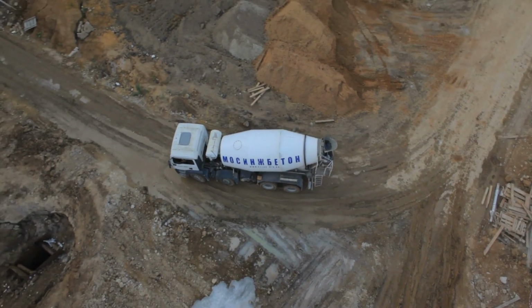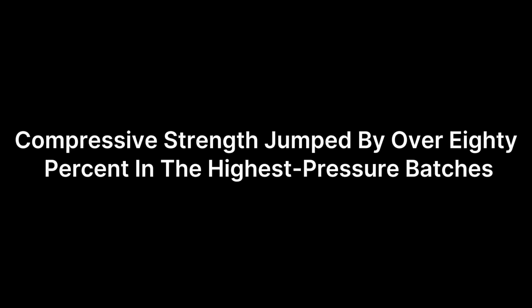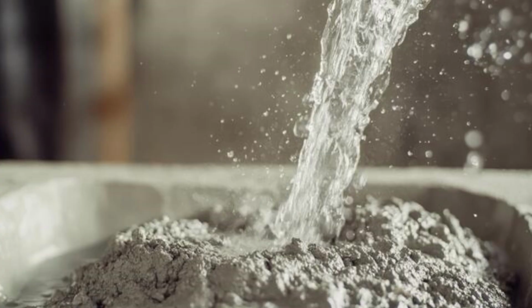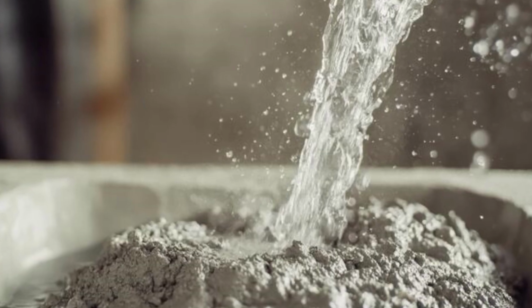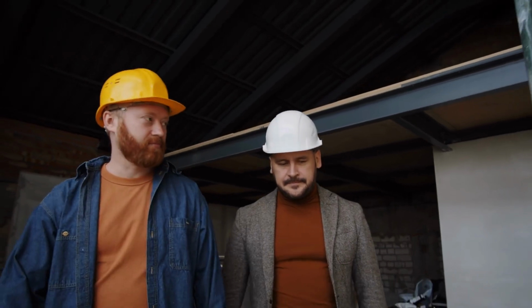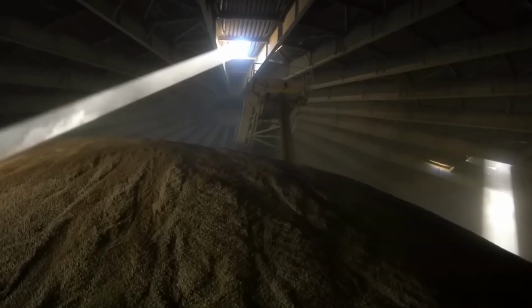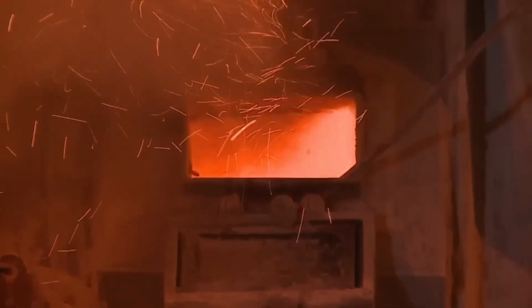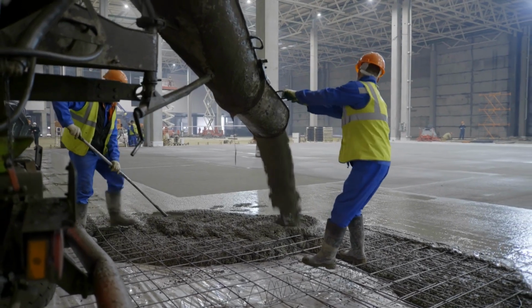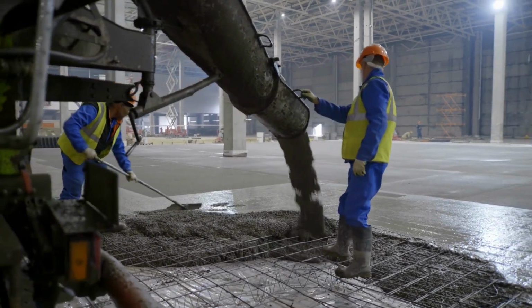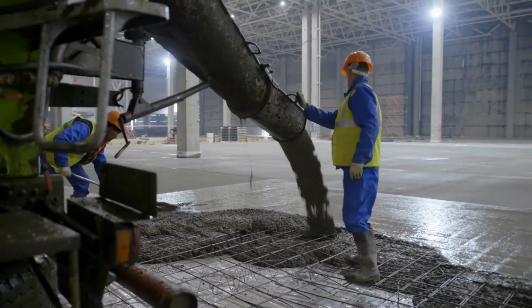Wait, what? And the lab results were jaw-dropping. Compressive strength jumped by over 80% in the highest pressure batches. Resistance to water, to freeze-thaw cycles, to chemical attack. All of it improved substantially. And here is the part that makes engineers sit up straight in their chairs. The team pulled all of this off without adding a single new ingredient. No expensive additives, no exotic materials, no new recipe. The exact same concrete, simply handled differently, produced a fundamentally superior material.